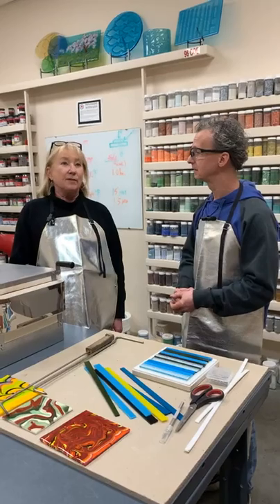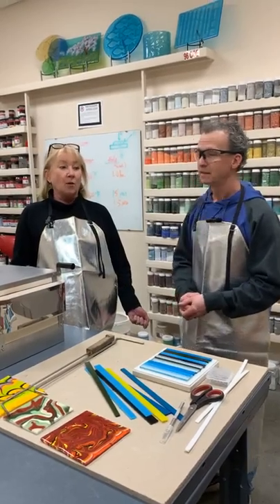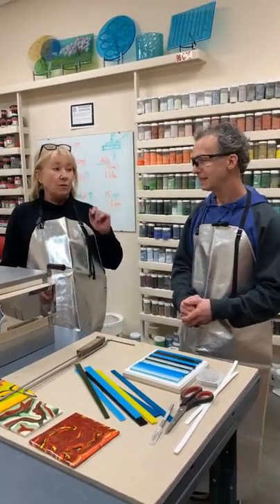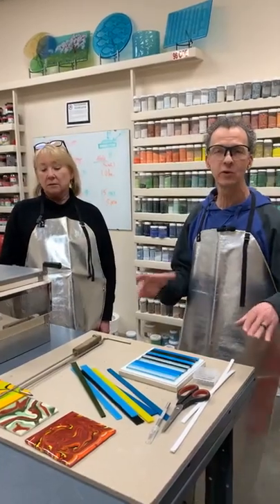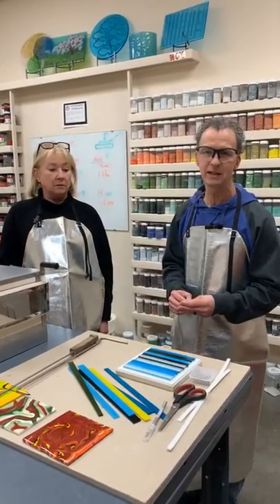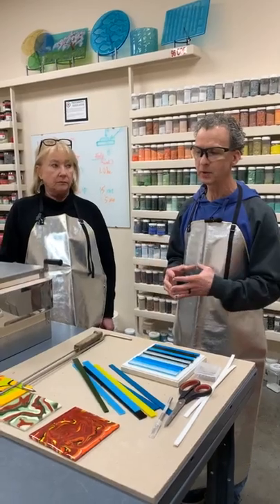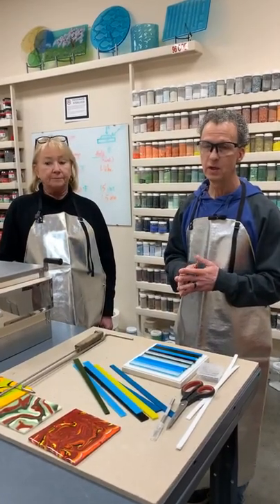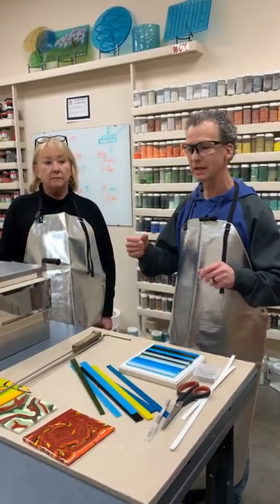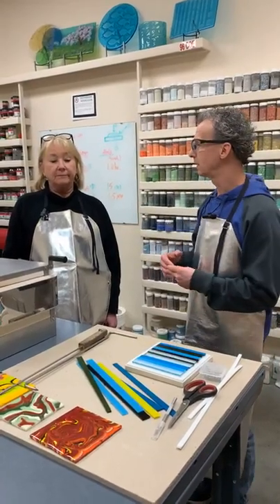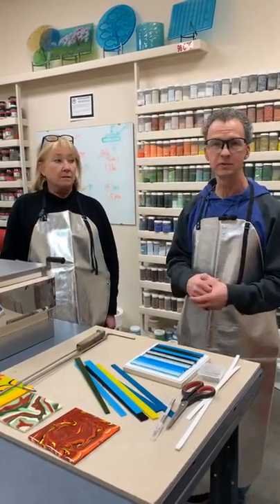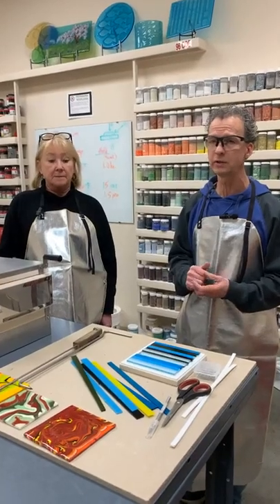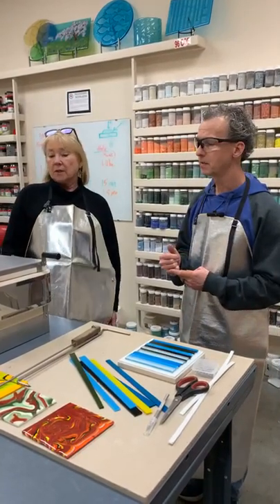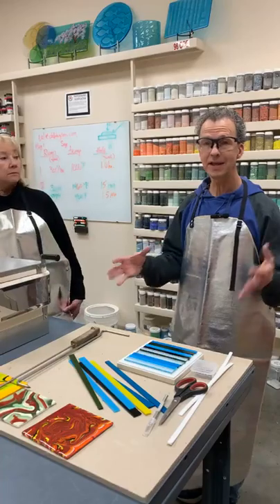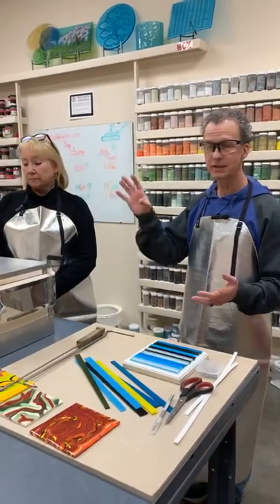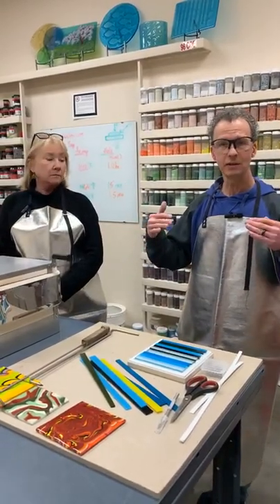Well, what is the temperature of the glass that we really want it to be, though? Yeah, if you're new to this sort of combing or raking technique, we're trying to get the glass pretty fluid, right? So we're trying to make sure that it's easy to rake into. And so I think Val and I both agree that we usually get up around 1700 degrees is the goal here. And I can tell you that the tricky part is getting the glass to 1700, because we can get the kiln up there, but the glass takes a while to catch up.